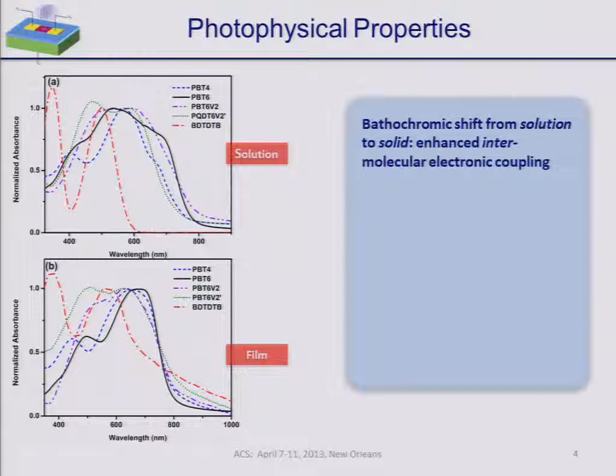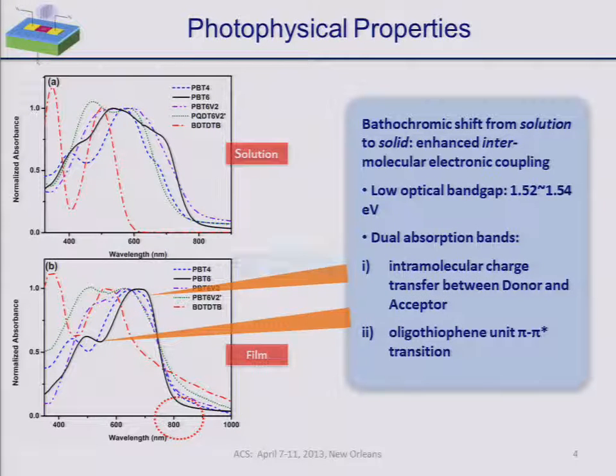If we look at the photophysical properties, we have solution state and solid film spectra. We see that there's a bathochromic shift if one goes from the solution state to the solid film, indicating that we do get good intermolecular coupling here. The materials have a low optical band gap, roughly one and a half electron volts, a little bit more than that. We see two absorption bands, one of which relates to the intramolecular charge transfer between the donor and acceptor, and the other, shorter wavelength absorption band, the pi-pi star transition from the oligothiophene unit.